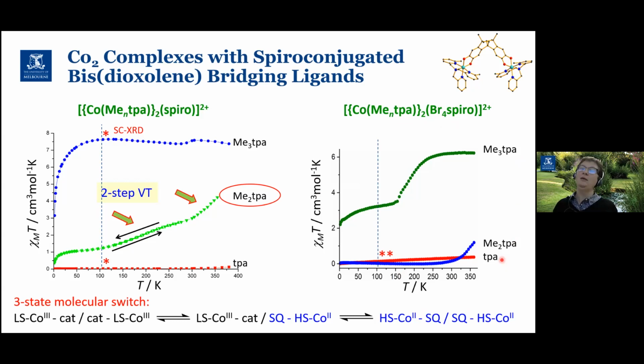Now the plain TPA analog, again, is as before, stuck in the low spin cobalt-3 catechol form at all temperatures. Things that are different though, the dimethyl TPA now is essentially diamagnetic up until about room temperature, and then there's just a bit of an uptick there. So in this case, with the bromo Spiro dimethyl TPA complex, we're just starting to see that first transition at one half of the dimer. And the crystallography at 100 Kelvin, the bond lengths are consistent with that. So we'll call that an incomplete VT transition.